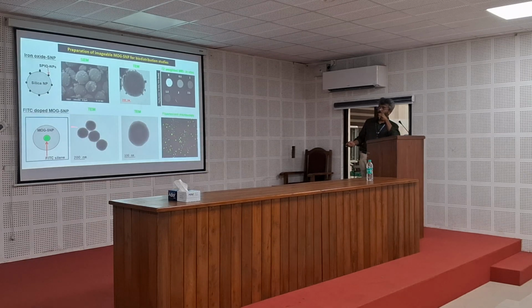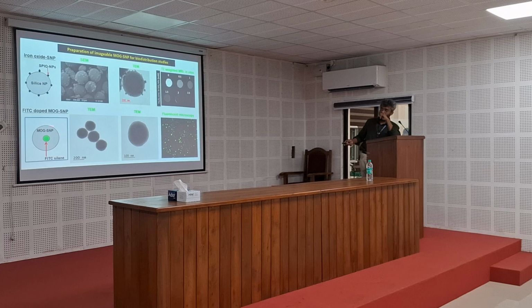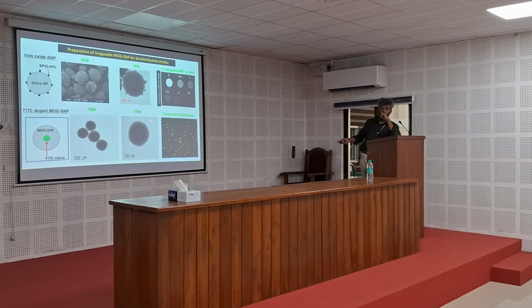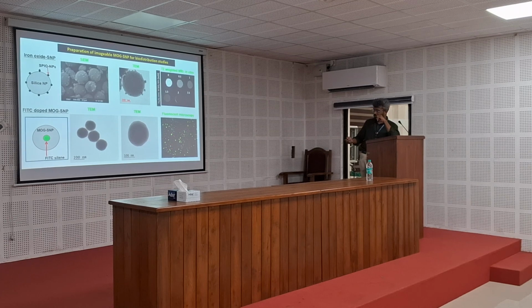Now we also wanted to image it using fluorescent microscopy. So we doped a dye inside the particle and developed these particles. This is the electron microscopy image, and this is the fluorescent silica nanoparticle. We can image it using a fluorescent microscope. So we have developed two types of imageable nanoparticles, one for MRI and one for fluorescent microscopy.